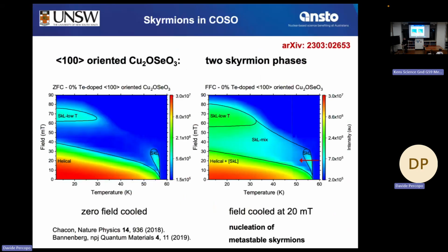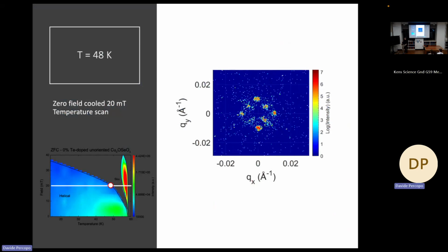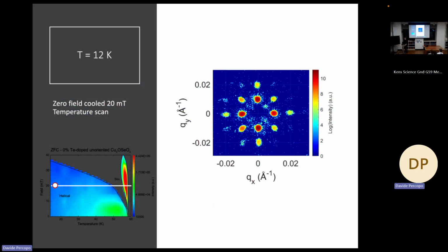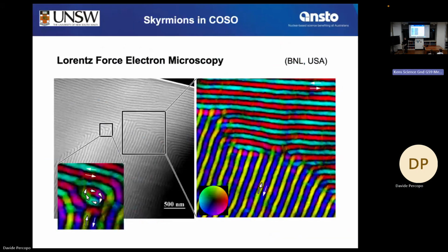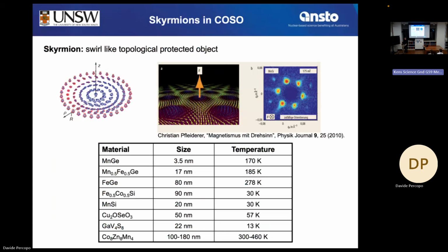Let me go back to the very beginning. It's a long video. Yeah, here is the table. 460 Kelvin, which is 160 above room temperature. Yes, and the other one, iron germanide, is 278 Kelvin. So we have a thin film of that material and it indicates that the phase transition is 300 Kelvin, which is around room temperature. As said, thin films are required for applications.